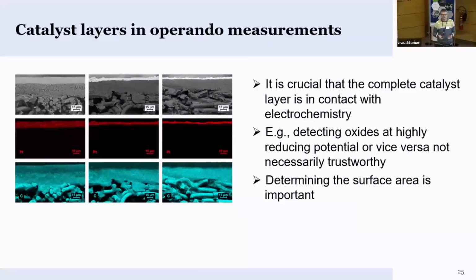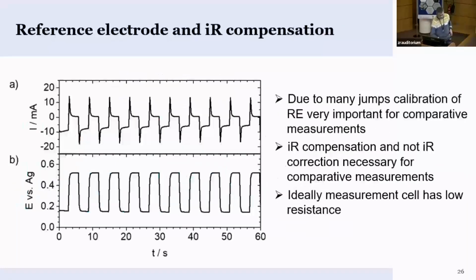And that you can only know if you measure the absolute area of your catalyst and compare it to the value you expect. Or the other way, if you detect oxide, I mean, in open circuit conditions in air, these catalysts are oxidized or reduced, and you have to see the response of the catalyst in order to know that it's actually in the electrochemical environment. That might not always be the case. So what we saw is very detrimental to the measurement, so it's also very important to guarantee that you have full contact of your catalyst layer.